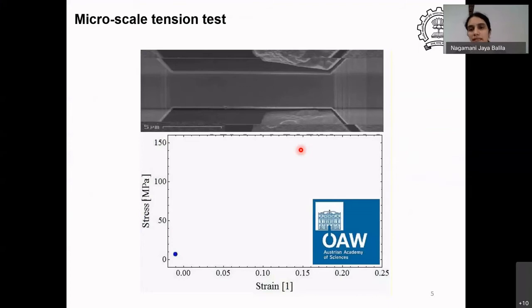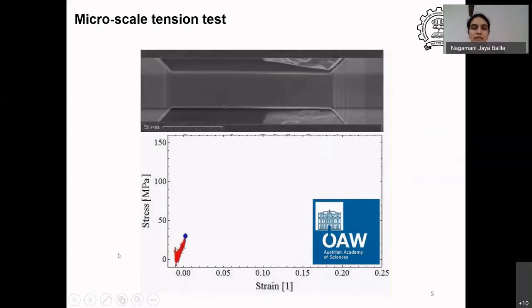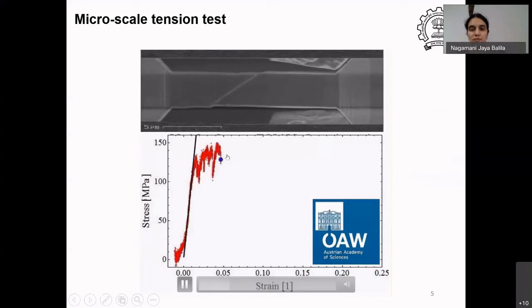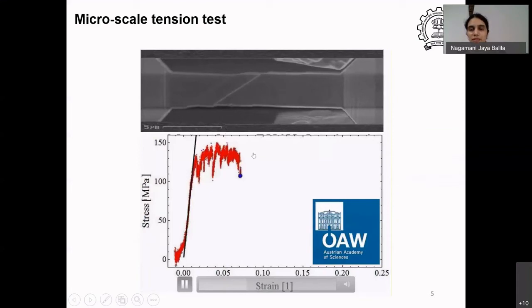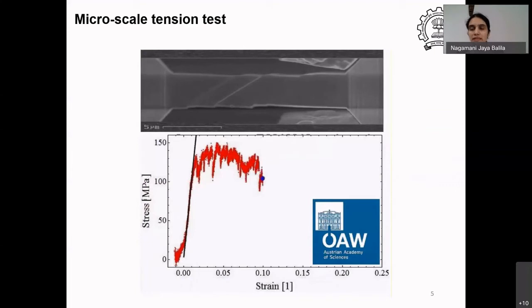If one tries to measure it in tension, it is possible but there are lots of difficulties. I'll still show a micro-scale tensile test — very much like what Professor Prita Pant was showing at the macro scale — but you now see certain differences. You see these load drops or corresponding stress drops. Every time there is some band appearing, you see these drops in the stress-strain curve. And this is what you will also see in the micropillar compression data.